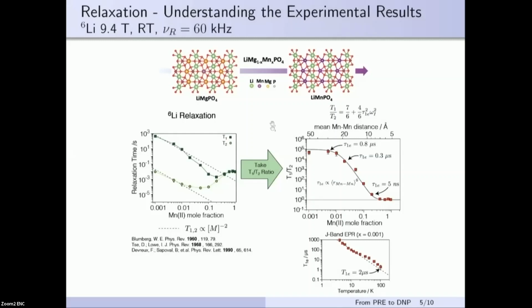One more thing that we can do is fit this curve, and we obtain that the electron relaxation time is proportional to the mean distance between manganese centers to the power of 6, which is a good indication that the reason for this decay in the electron relaxation time is the through-space electron dipole coupling.